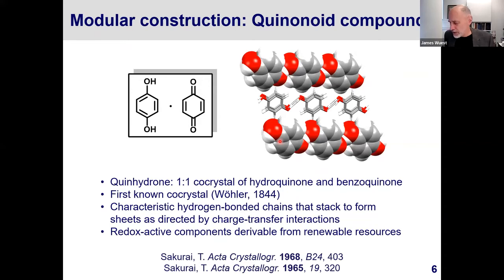So I don't want to spend too much time talking about modular construction, but in the last few years, we've embarked on a series of studies in this area that involve co-crystallizations that are directed by hydrogen bonding and also by charge transfer interactions. If you co-crystallize hydroquinone and benzoquinone, many of you understand that this pair co-crystallizes to form what's called quinhydrone. So quinhydrone is a one-to-one co-crystal of hydroquinone and benzoquinone.